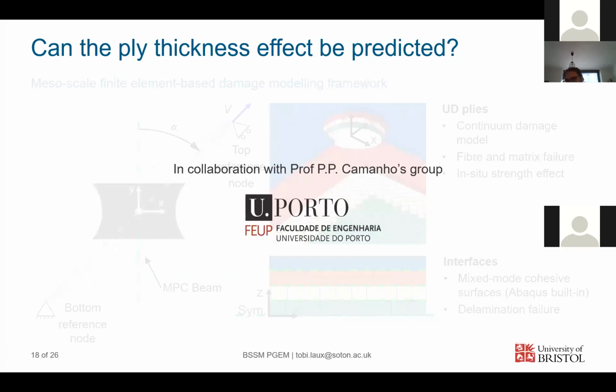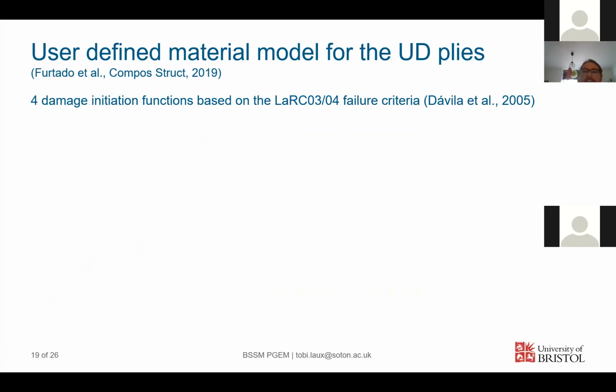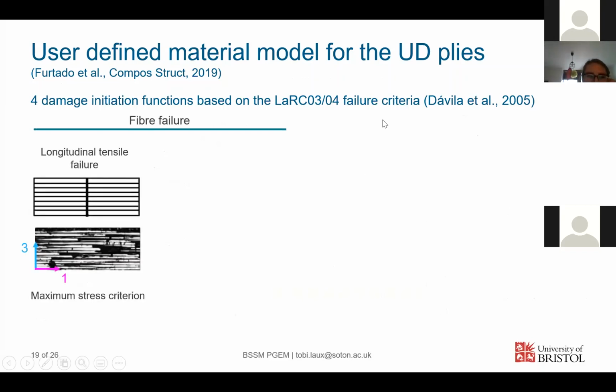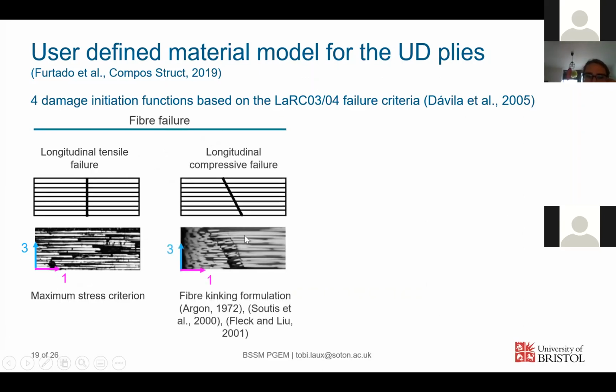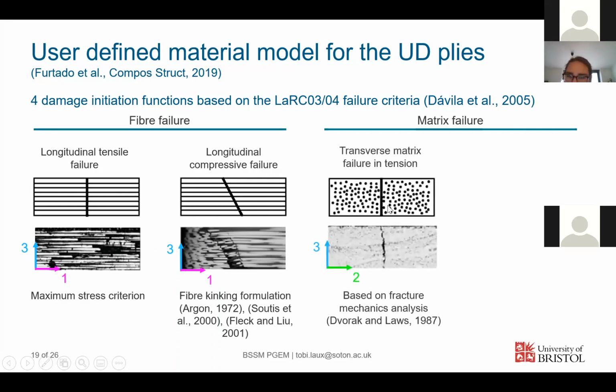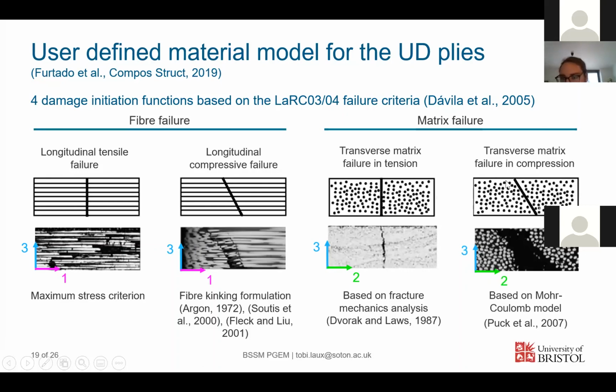So this was done in a collaboration with Professor Camanho's group at the University of Porto, where they have really an advanced modeling framework for the UD plies, which we used for this work. So a bit about this damage model for the UD plies. So we predict fiber failure in tension, which is just a maximum stress criterion. There is a model for compressive failure, which is a kinking criterion. And then we have two types of matrix failure. It's matrix failure in tension and matrix failure in compression, where you get an angle. So all of this is implemented in this model, and we can predict.